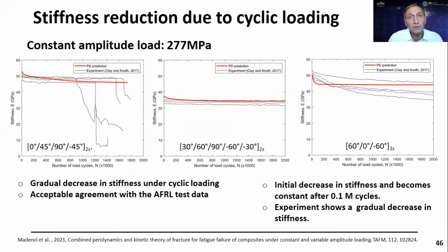Here we have the stiffness reduction due to cyclic loading. So we basically compare what we predict against the experimental results. For the first two, I think Peridynamics does a very good job capturing the gradual decrease in stiffness under cyclic load. And it's an acceptable agreement. But for the last one, there's an initial decrease for about 100,000 cycles, and then it pretty much becomes constant. But the experimental results show a gradual decrease. So I don't know what the reason is, but this is what it is.